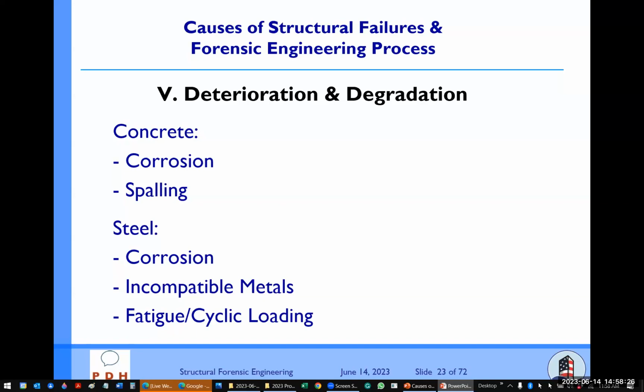So epoxy coated rebars are one of the solutions, and adequate concrete coverage is another solution. As you know, when rebar in the concrete corrodes, it expands several times the original material, and that force is enormous and causes cracking and spalling of the concrete. So be careful whenever you see efflorescence on a concrete material, or on a reinforced CMU wall, a masonry wall. Corrosion can happen there. Obviously, it cannot be life-threatening within the first 6 months or a year, but over the course of years, you saw what happened in Florida. It can be very, very destructive.